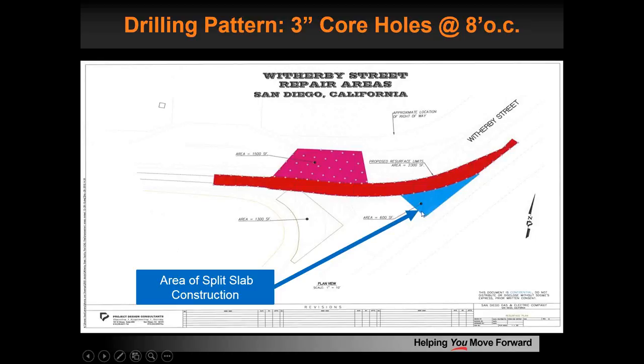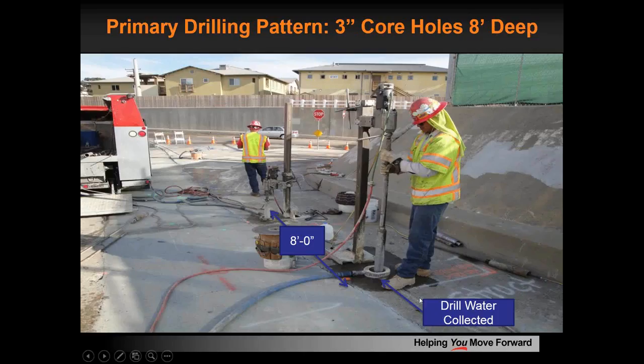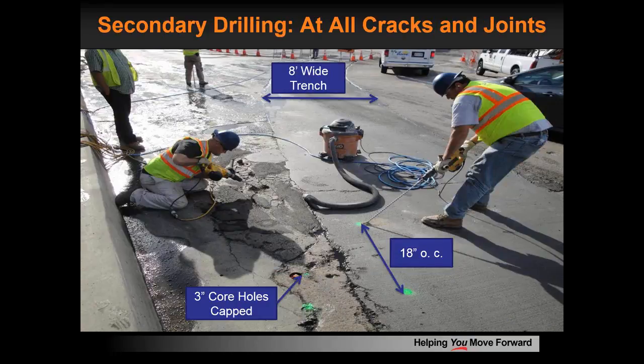This blue area shows a zone where they actually chipped out 28 inches of concrete, put in a membrane, and put the concrete back, and that lasted about 7 years, and then that started to leak. So here we are, core drilling on the outside of that 8-foot trench, and while we were working, 3 of the 6 lines were always active, so we had to do this work while there was energy going through the system. We're doing a little interception grouting here at the joint, and in these we used a 30% acrylamide solution,